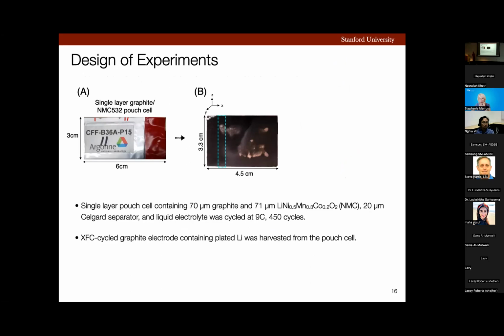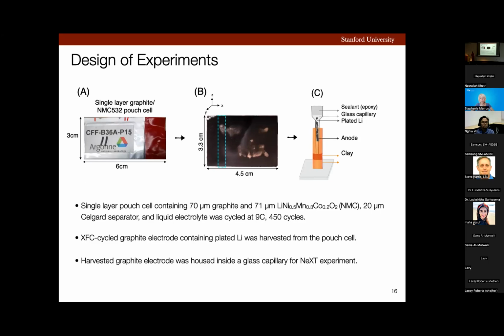And then I cut a strip around this blue dotted rectangle here. I cut a strip because it's very difficult to 3D image a full flat pouch cell. And then the strip was put in a glass capillary, which was then used for the next experiment. Here, I would like to note that during sample prep, lithium was exposed to moisture in the air. And because lithium is so reactive, it formed lithium hydroxide. So any lithium-containing protrusion that I would be showing in this work is lithium hydroxide.